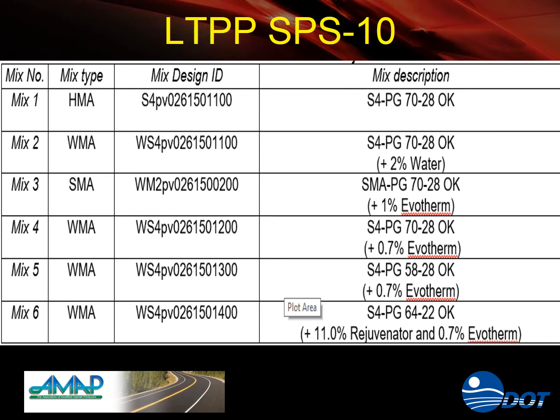Well, in that SPS-10 project, we have 6 mix designs that we looked at. There's the layout of it. And our mix design terminology means something. This S4 is our surface mix, half-inch nominal maximum size, 12.5 millimeter, and then design lab number, and then the year it was designed. And then 0 usually indicates the original binder, and then 11 mix designs this lab has performed, and then 0 corrections to the mix design, and 0 job mix formula change. We only allow 3 job mix formula changes before they have to remix.